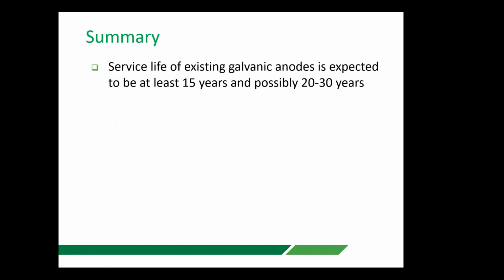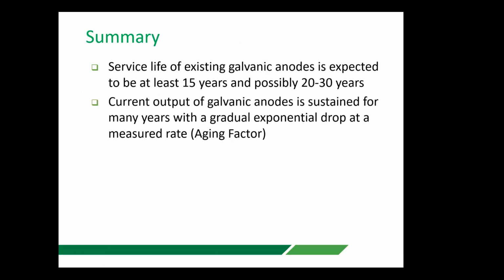So just a summary, the service life of existing galvanic anodes is expected to be at least 15 years and possibly 20 to 30 years. We're more confident that we can get to 30 years now with new technologies and the improvements that were made to the anodes from learning of our mistakes, if you like, or understanding the behavior of anodes. Current output of galvanic anodes is sustained for many years with a gradual exponential drop at a measured rate. And that measured rate we are now calling the aging factor. So the higher the aging factor, the better the performance of the anode.